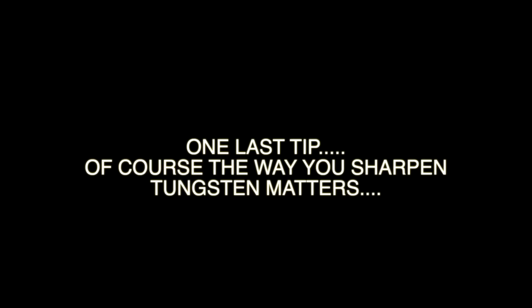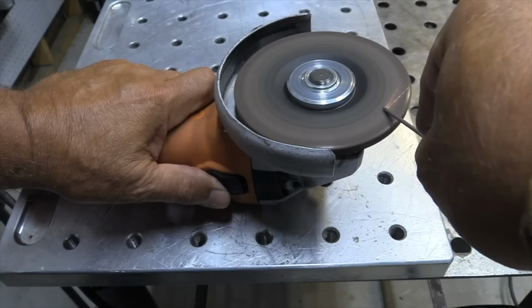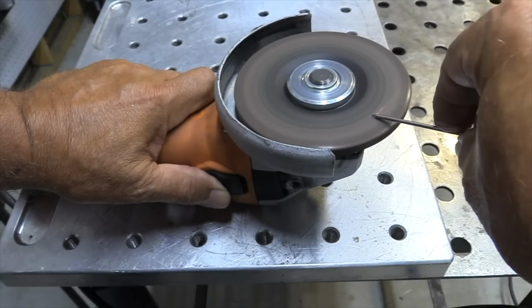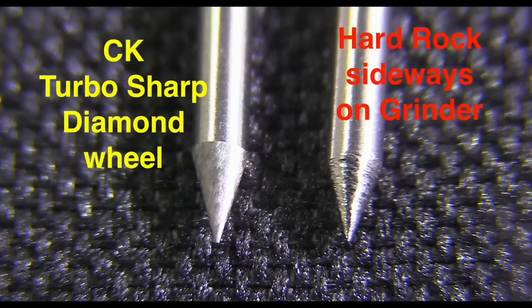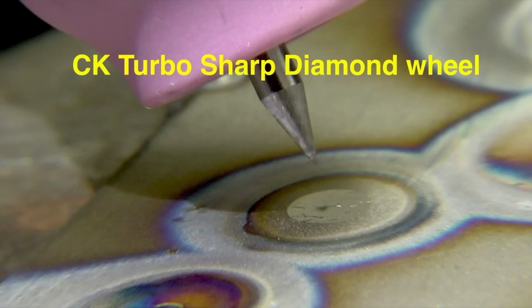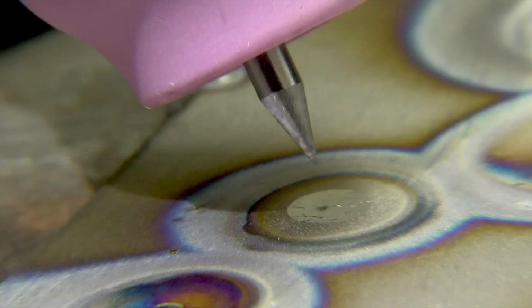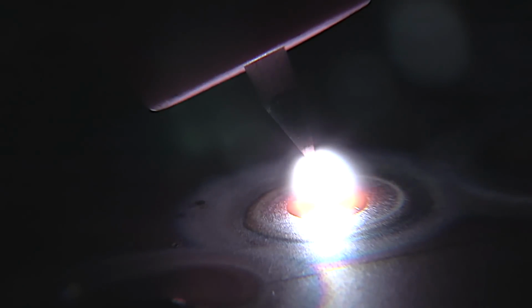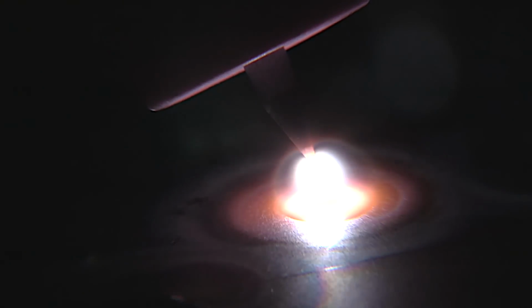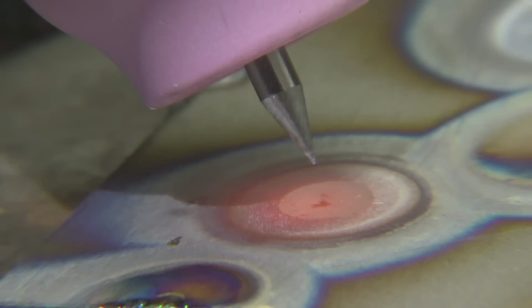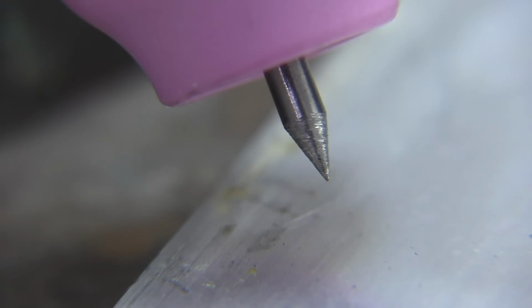And of course, one last tip. It does matter how you grind an electrode, how you sharpen an electrode. Mainly what you don't want to do is make your grinding scratches sideways and make them rough. If you're using too rough a wheel and you put the grinding scratches sideways, you can have some really rough arc starts. Let's compare one sharpened by the Turbo Sharp that has a diamond wheel, so it puts a really fine grind on there. That's a nice crisp arc start. That's what you want. Now let's take a look at the other one done with a grinding wheel, scratches rough and sideways. You can get some really rough arc starts that way with a wandering arc.